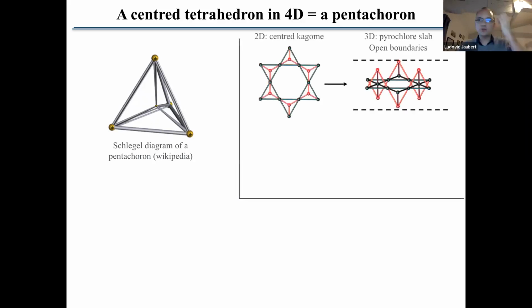The way to understand it is to go one dimension below, as we discussed previously, and consider the 2D centered Kagome lattice, with the Kagome lattice sites as the black dots and the centered spin as the red one. You can see it as a slab of a pyrochlore lattice. If you take this spin and make it up, and take this one and put it down, alternating above and below the Kagome lattice, this is exactly a slab of a pyrochlore system.